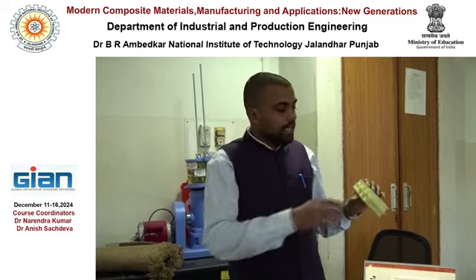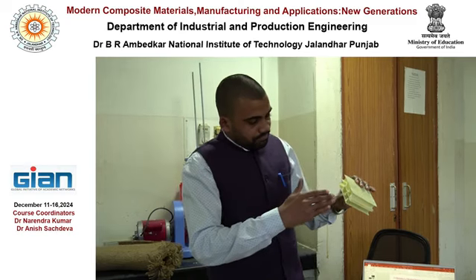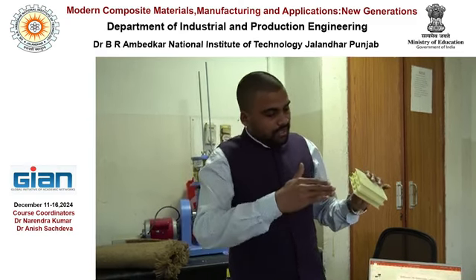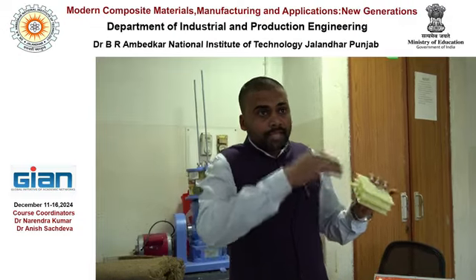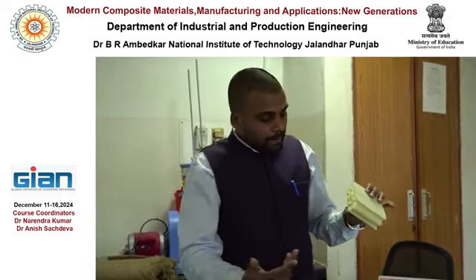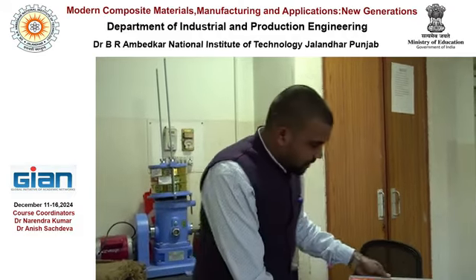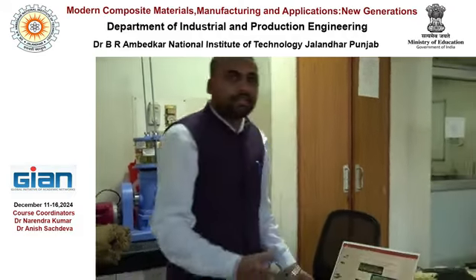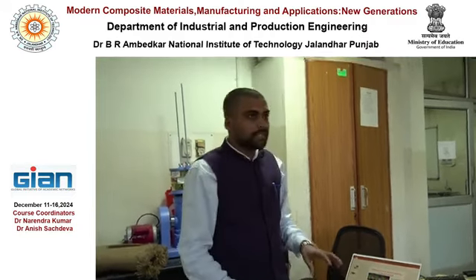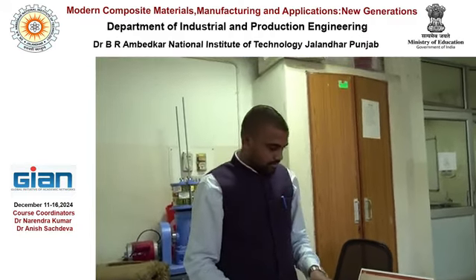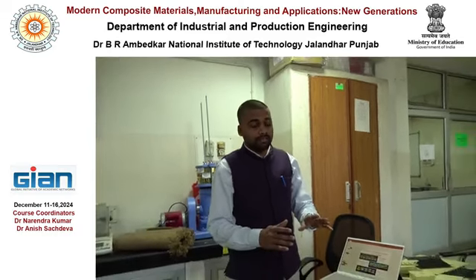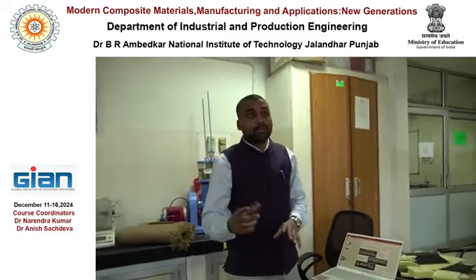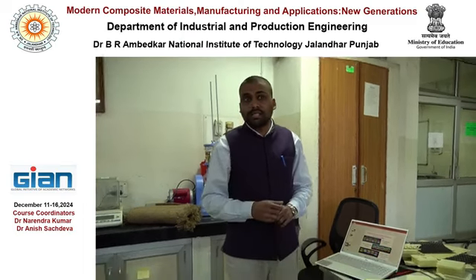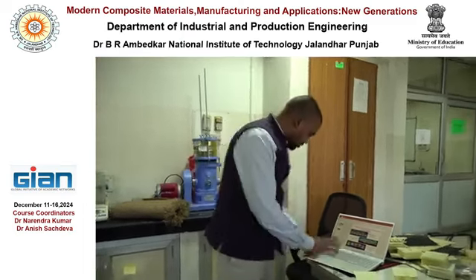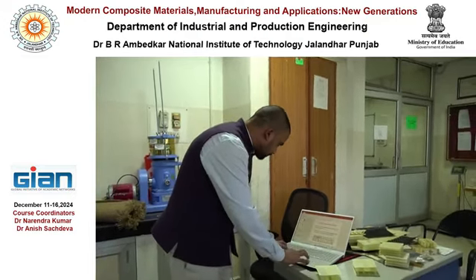So efficient energy transfer will happen only when the bonding between these layers is proper, and since it is stuck by the matrix material, it will not bear as much load as compared to your integrally woven preforms. So let me show you the integrally woven preforms.